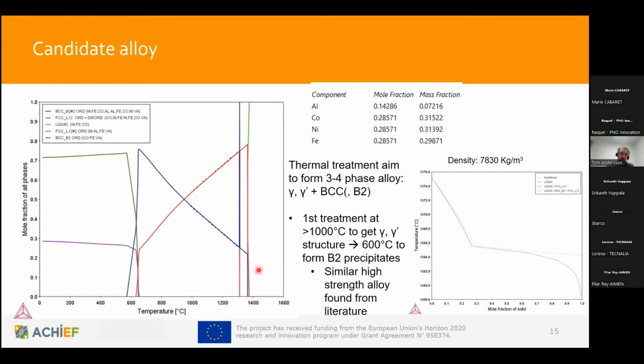And it seems to be quite promising, since there is quite a high amount of FCC, or this gamma prime type of phase that is known to be beneficial for these high temperature alloys. And also there seems to be this kind of BCC B2 type of mixture there. So we would end up with this kind of dual phase material of FCC and BCC, and we are aiming at this heat treatment so that we could form this gamma prime phase mixed with this BCC B2 phase that seems to be, according to literature, quite good, or have quite high strength.